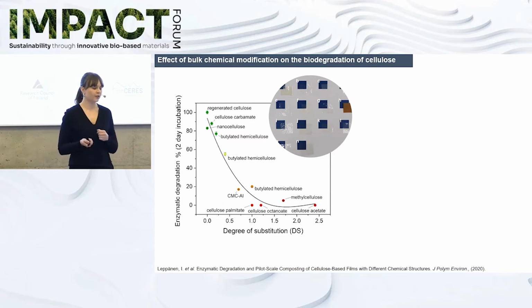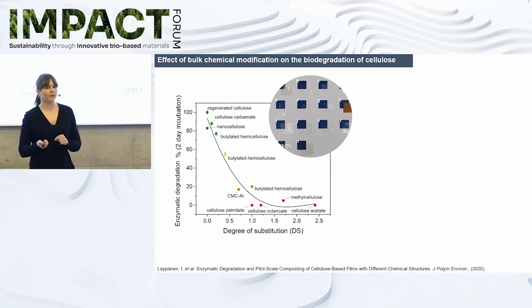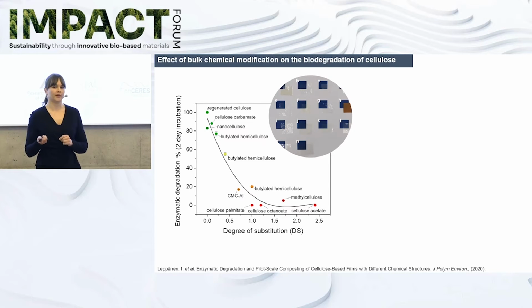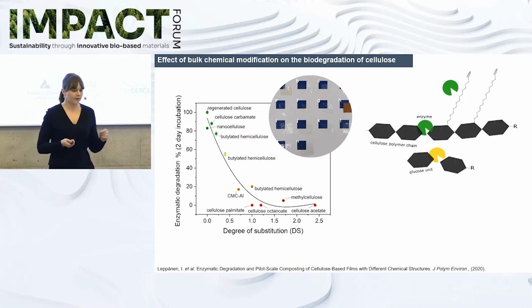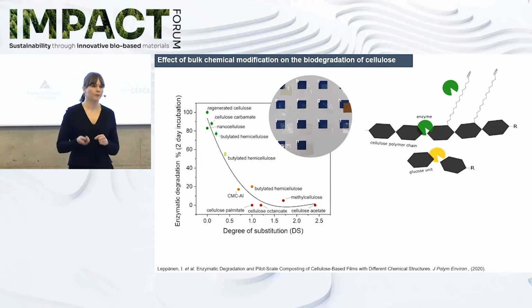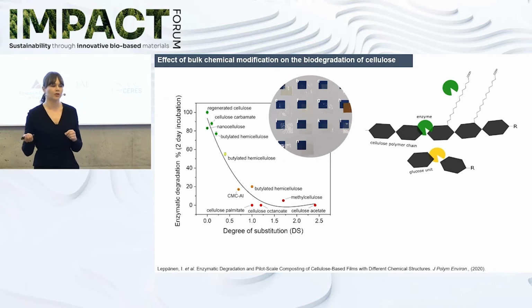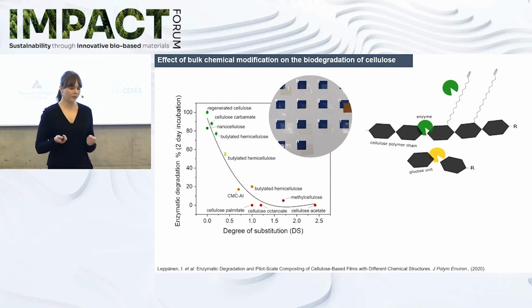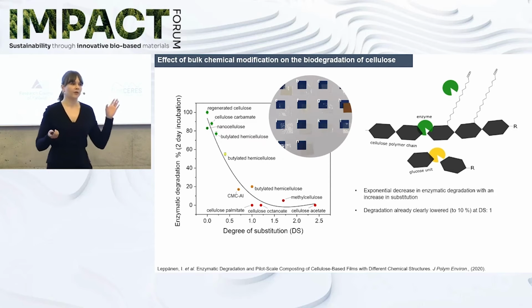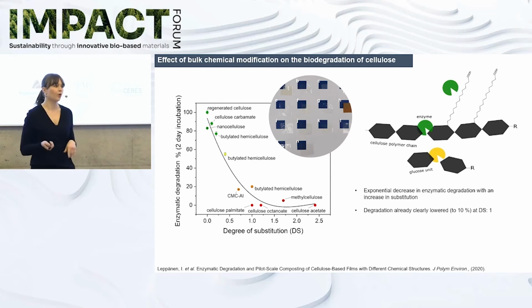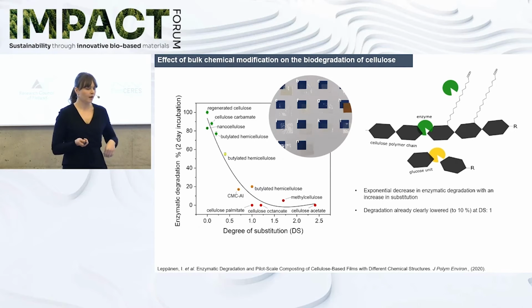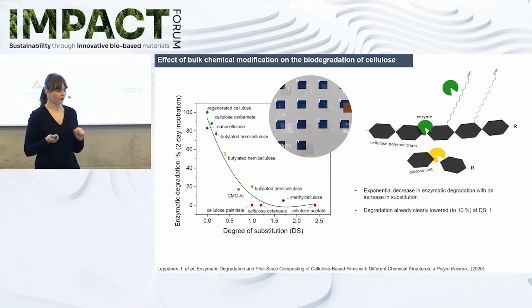So we see that, for example, for regenerated cellulose, which is natural unmodified cellulose, it has a 100% degradation already in these 2 days. But then on the x-axis, where we have the degree of substitution, the more we modify the cellulose, the more the enzymatic degradation decreases. Basically this is because we have these longer substituent chains, and it actually blocks the enzymes from attaching to the polymer and breaking it down into glucose units. And we see that there is a really exponential decrease, and the degradation is already clearly lowered at a degree of substitution of 1. So we really need to have fine control over the modification so that we're able to retain the biodegradability.